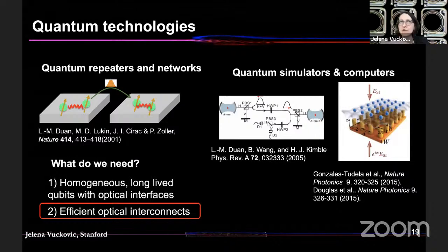And also relative to cavity QED platforms with quantum dots, this is getting to a comparable range to what we and others have demonstrated some number of years ago. Ultra strong coupling regime, for example, that circuit QED platforms can be used to demonstrate, I think that's out of the question in these systems, because you basically always operate with lossy cavities, and your coupling strengths are not so large that you can observe the ultra strong coupling regime. You can observe strong coupling, but you are always operating in the regime where you have a bad cavity, basically.